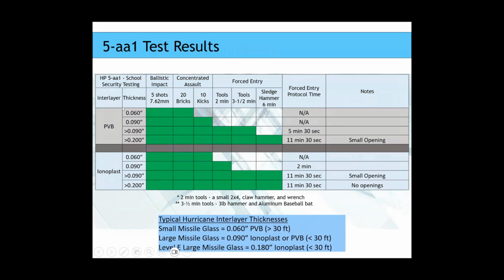In this chart here, this is the 5-AA1 test showing how far the glass survived the testing. We did different thicknesses of PVB and different thicknesses of ionoplast. In general, the ionoplast, because it's stronger and more tear resistant, lasts much longer in the testing for the same thickness. But note, 60 mil PVB, or 1.52 millimeter PVB, is what's normally used in a small missile test. It really did not perform very well. It didn't even make it through the brick test.